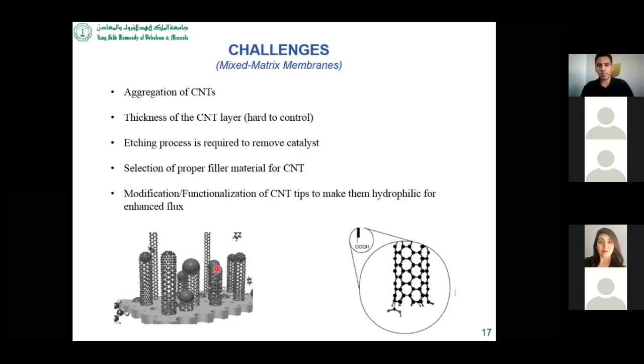Secondly, this is the carbon nanotube produced, and this is the catalyst. During production, especially in the CVD, the carbon nanotube will grow on a specific catalyst, usually an iron-based catalyst. Now, for various applications, you need to remove this catalyst. There are some ways to remove this catalyst, but of course, it will damage the properties of the carbon nanotube. For example, acid treatment is commonly used. But what is the problem in the acid treatment? It will remove the catalyst, but it will reduce the length of the CNT, or sometimes it will break the CNT. So again, there is potential in this area. You can develop some techniques to develop a most efficient way to remove this catalyst from the CNT.